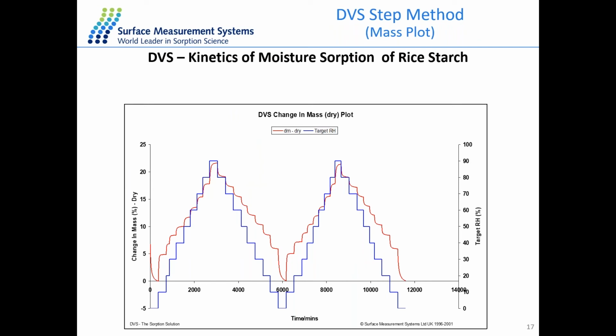And then we will go through some kind of application with the DVS technique. So we basically have two very typical methods for the DVS measurement. The first one is the step method, just as we introduced in the previous slide, where we increase the humidity step by step. So here's an example with the rice starch sample showing the kinetics information about this moisture sorption.